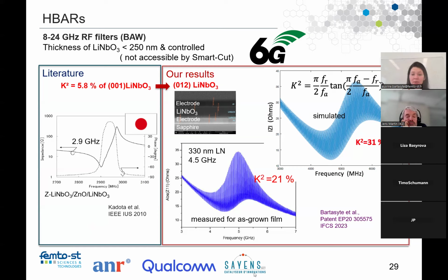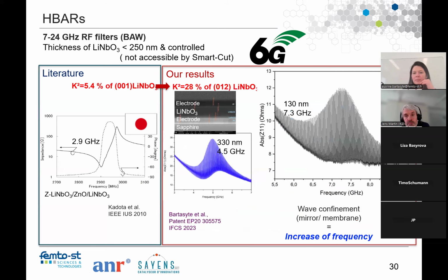Here I show you an example where it's not exactly the same coupling. We see that the film has lower coupling, but on the same wafer. Finally, I also found the coupling exactly as expected theoretically. So it really depends. In some places, the films are self-polarized, which is nice, but still we need to be reproducible and to do poling everywhere to get everything repeated. But we were able to get to quite high frequencies, like 4.5 gigahertz, 5 gigahertz, and so on, depending on the thickness of the film.